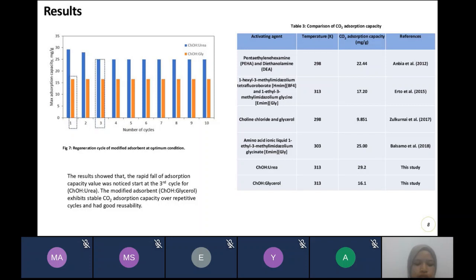Regeneration is an important aspect to restore the adsorption capacity of the exhausted adsorbent for carbon dioxide capture. Adsorption and desorption experiments were carried out for a total of 10 cycles. The modified activated carbon with choline hydroxide and glycerol showed a good regeneration ability up to 10 cycles. Meanwhile, for the modified activated carbon with choline hydroxide urea, a rapid drop of adsorption was noticed beginning from the third cycle. However, the adsorption value from the third until the 10th cycle was maintained.